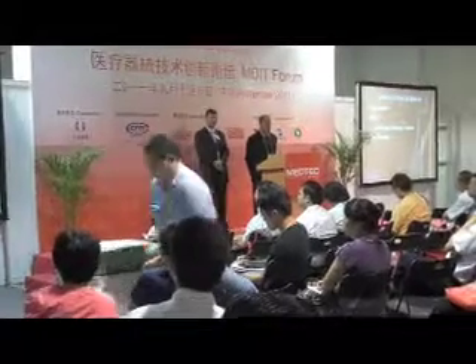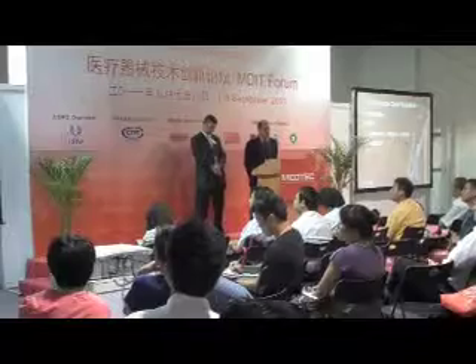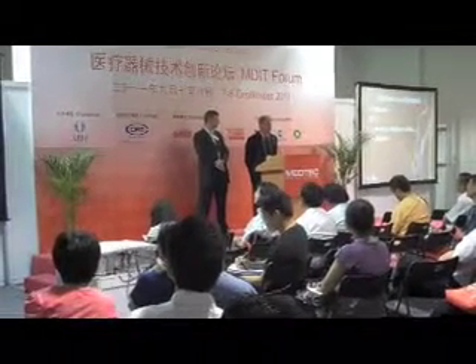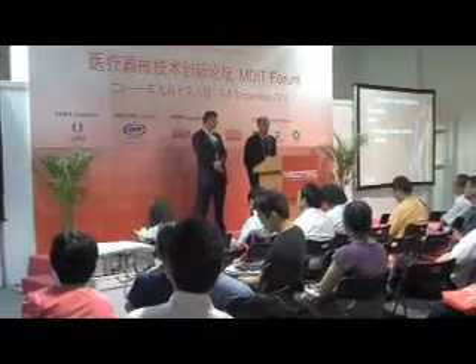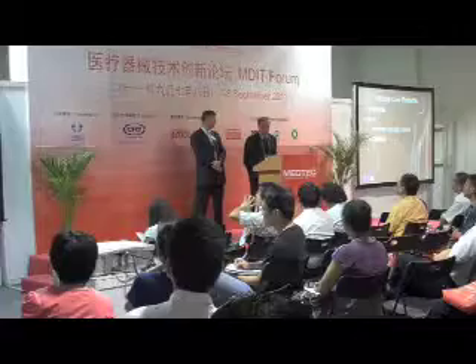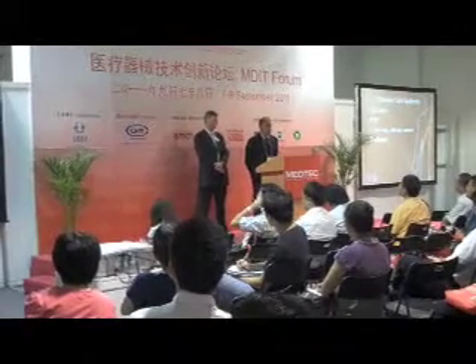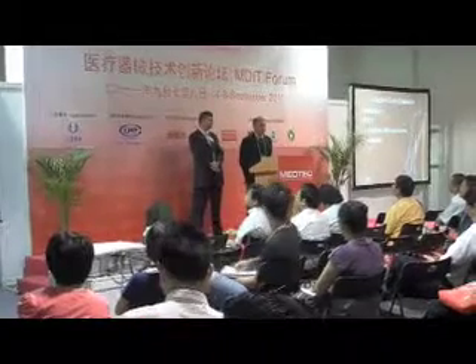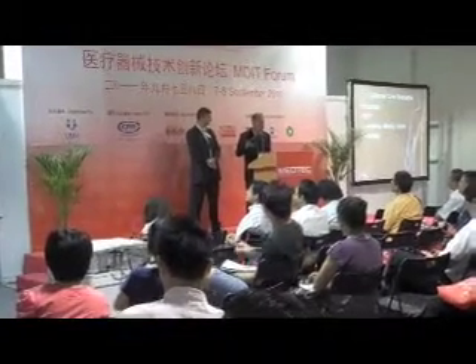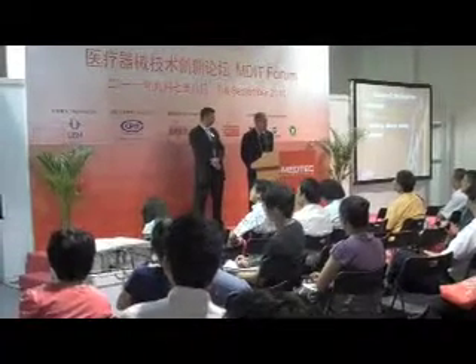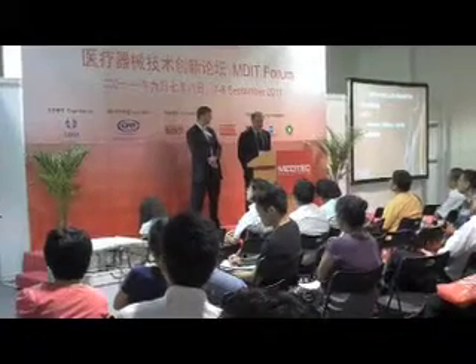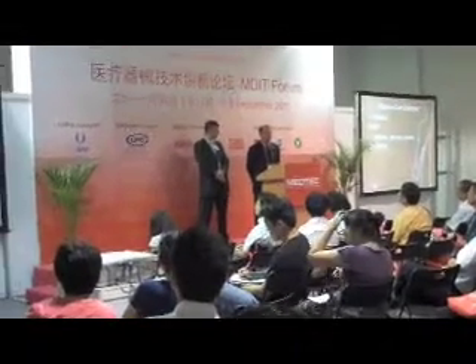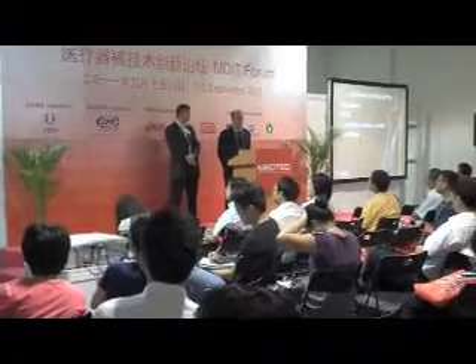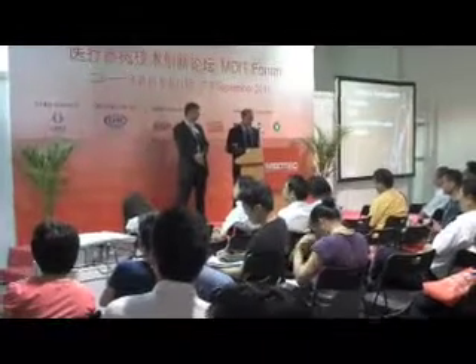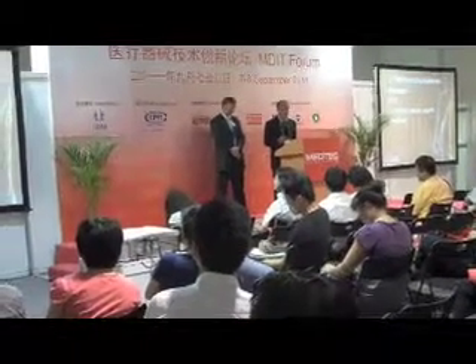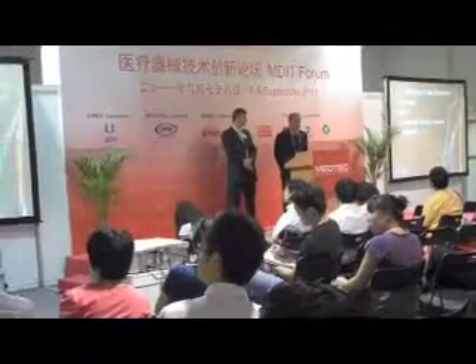Disadvantages would be that they cure very slowly. And finally, the materials that SSF is working most with in drug delivery right now are what are called platinum catalyzed addition systems. These materials typically cure at elevated temperatures, but as we'll show in a little bit, the time-temperature combination can be adjusted so that you can work with most drugs. I guess what I didn't add here is that these drugs, or these active pharmaceutical ingredients, tend to be unstable at high temperatures. So one of the real concerns we have is choosing a silicone vulcanization, choosing a material and the process that allows us to cure the silicone below the decomposition temperature of the drug.